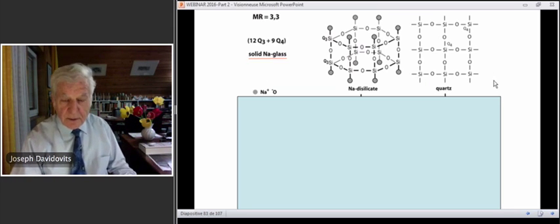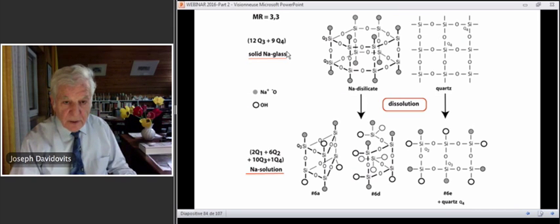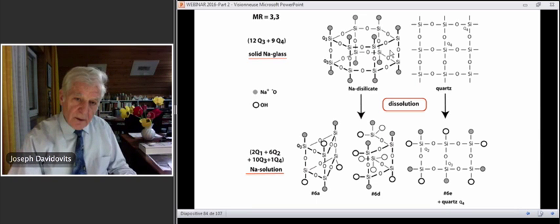To show them in a better structural way, this is what you get in your glass, made in the furnace, solid sodium glass. These are the structures that you get, complicated structures, and they are dissolved in the autoclave in the factory in order to produce the solution that contains these types of molecules: molecules with 1, 2, 3, 4, 5, 6 silicon oxygen bonds. These are heptamers. These are the oligomers that I was talking about at the beginning, and they have different shapes. Some are linear, some are completely cyclic, three-dimensional, and this is a two-dimensional one. And they will interact with the other system totally differently.